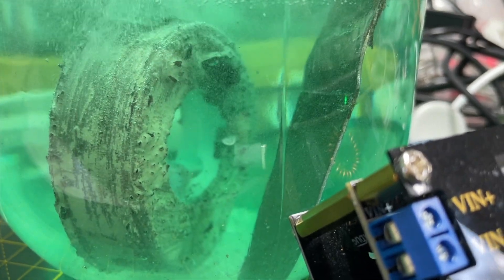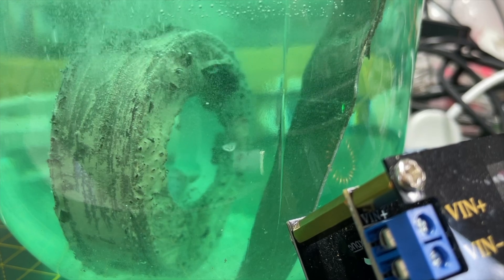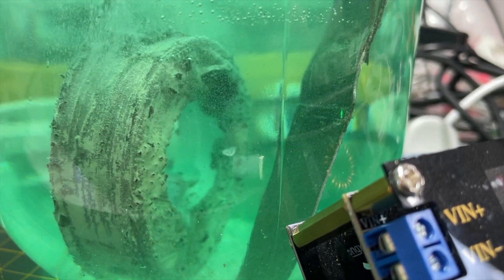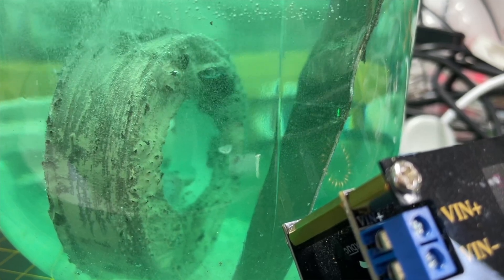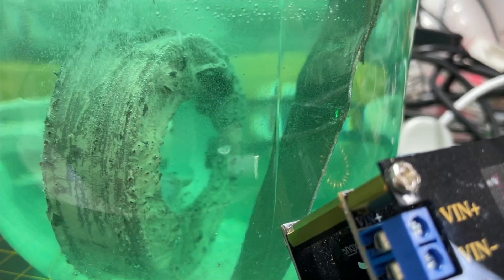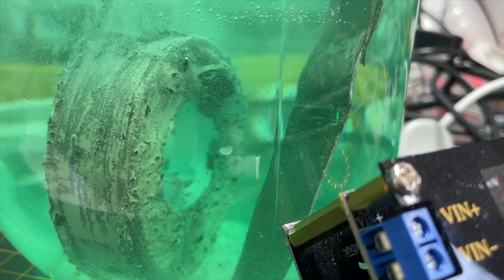What's happening is a lot of the bubbles are forming underneath the silver coating and that's pushing the silver coating away from the 3D printed surface, making it very uneven. Let's have a look at this once it's finished and take it out to investigate.